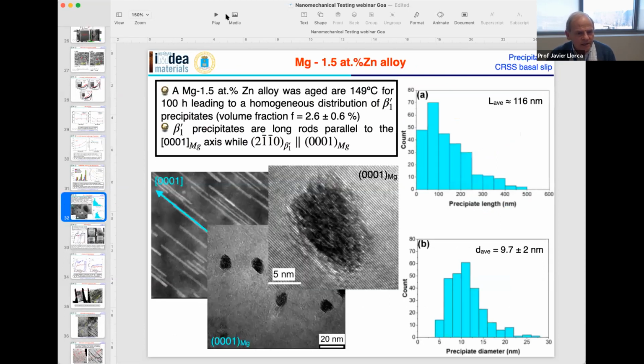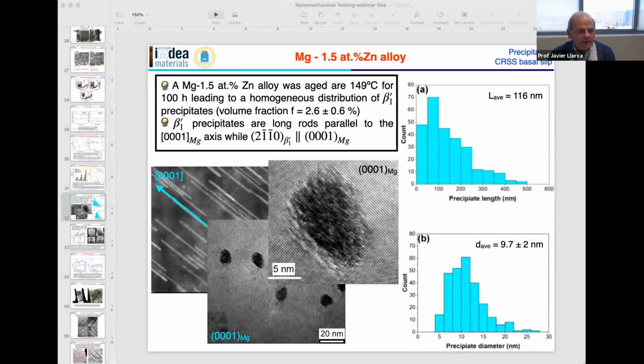So again, I'm going to change to the presentation mode. What we did is take a magnesium 1.5 atomic percent zinc alloy, and then produce a very nice distribution of beta prime 1 precipitates. These beta prime 1 precipitates, as you can see, are long rods that are parallel to the c-axis of magnesium. This is the cross-section of these long rods. You can see they have a diameter of about 10 nanometers.